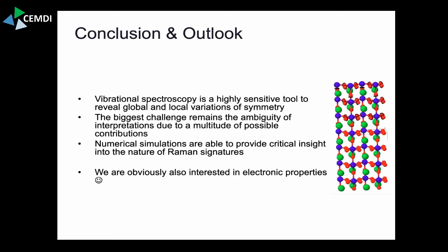I can be a little bit more specific on that, because we're following up on this. So magnesium oxide, for example, is extremely hydrophilic. That's why you use it in sports to dry your hands, because it just sucks up moisture. There is chemisorbed moisture, which actually translates, for example, to Mg(OH)2. And then there is physisorbed moisture, which is just surface-bound water. And they have a Raman signature, and that's something we can detect. It's a very clear signature if it's really a different chemical molecule or any kind of ligand. Water is a very common ligand.